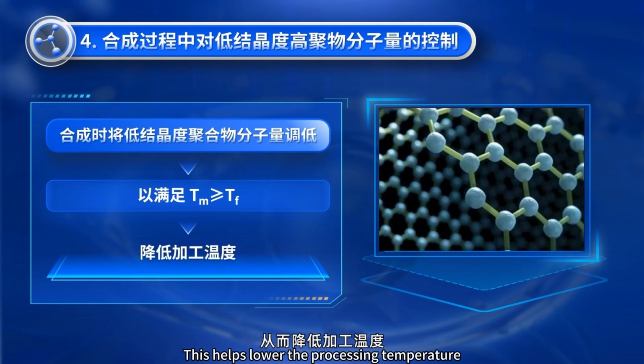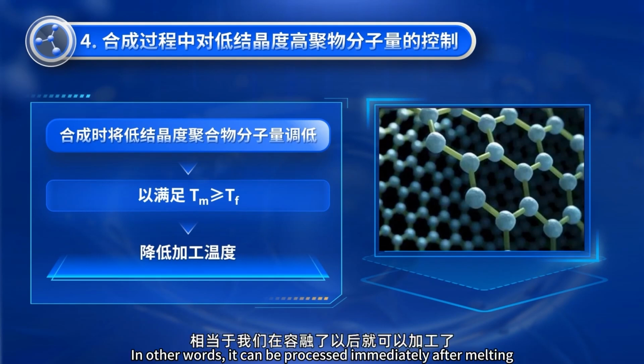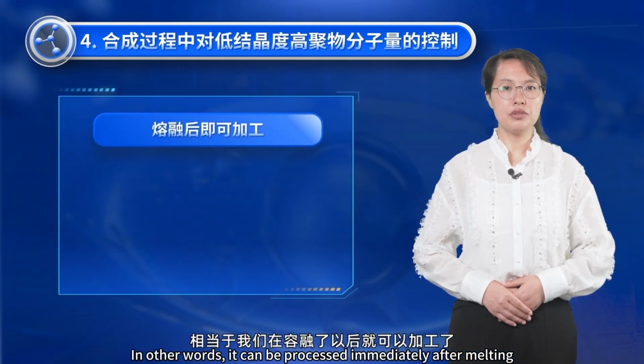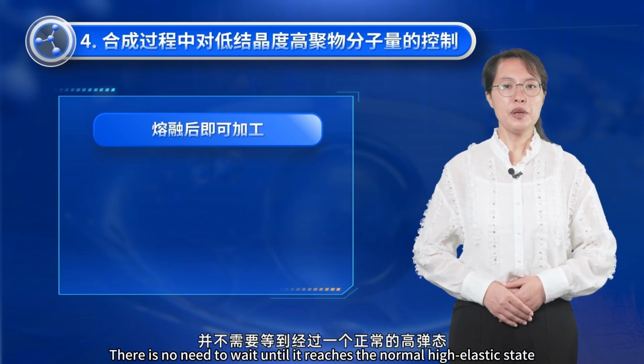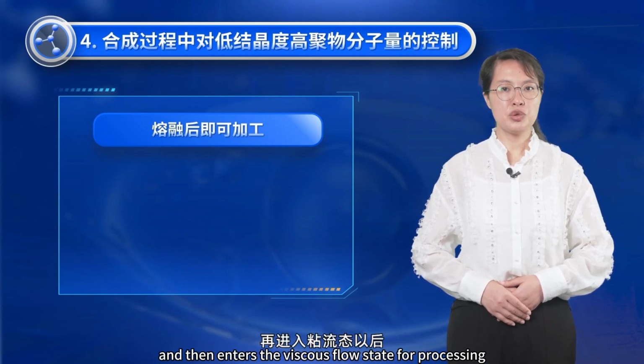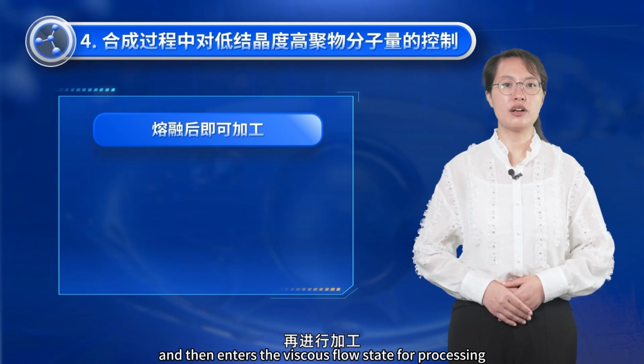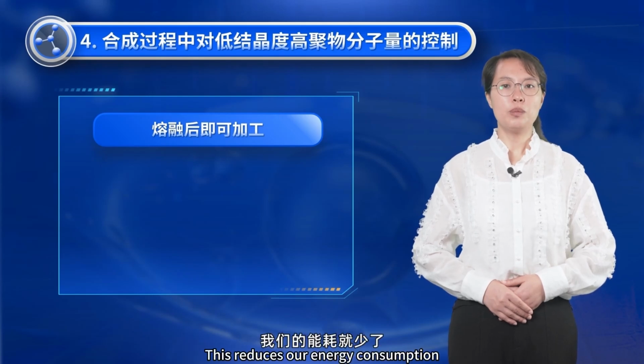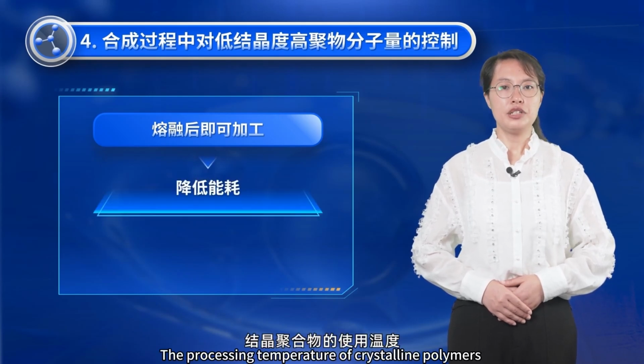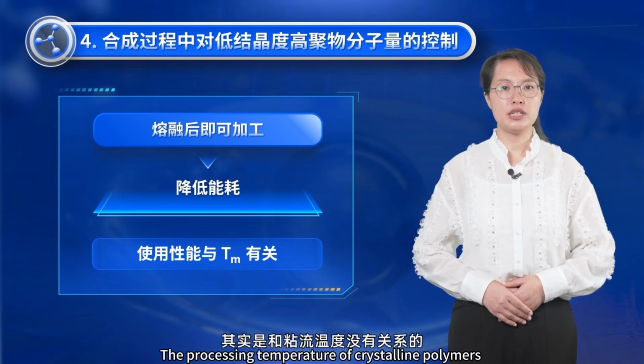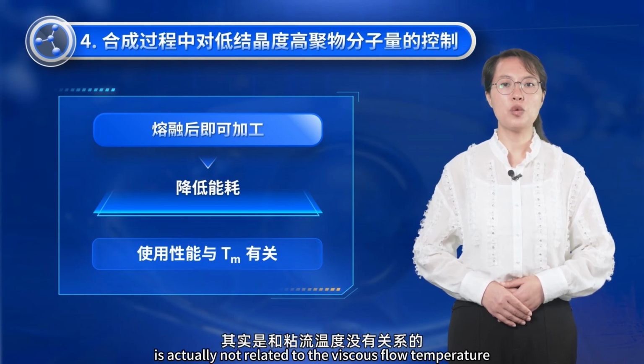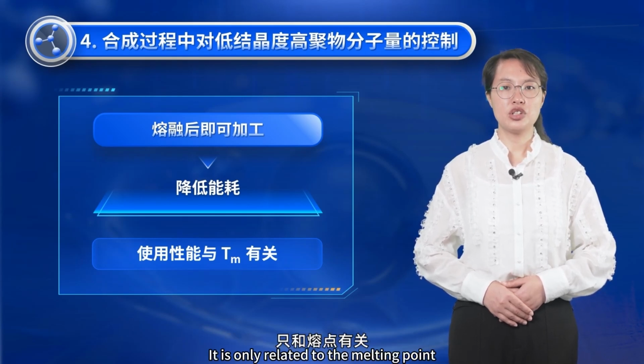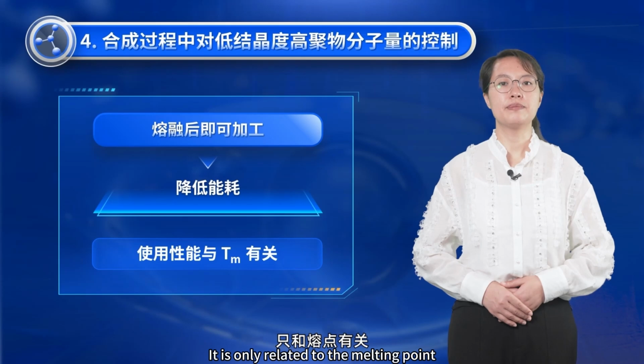This helps lower the processing temperature. In other words, it can be processed immediately after melting. There is no need to wait until it reaches the normal high elastic state and then enters the viscous flow state for processing. This reduces our energy consumption. The processing temperature of crystalline polymers is actually not related to the viscous flow temperature. It is only related to the melting point.